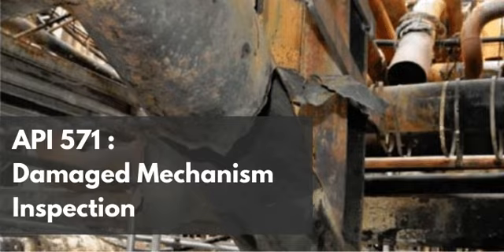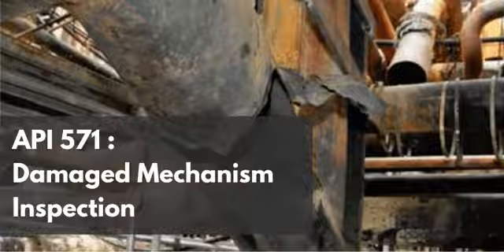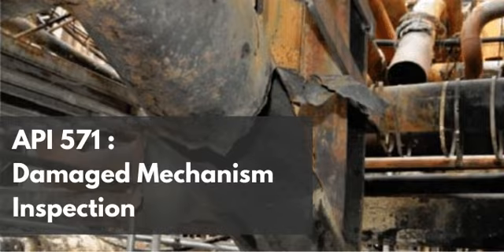Wow. The mechanical action of the turbulent fluid accelerates the chemical action of the corrosion. This synergy results in deep, aggressively localized metal loss that eats through the wall thickness incredibly fast. All while the straight run of pipe right next to it might look relatively untouched because the flow there was smooth. Unbelievable. So velocity and turbulence are the physical drivers dictating where the damage concentrates. But we also have complex chemical concentration effects to worry about.